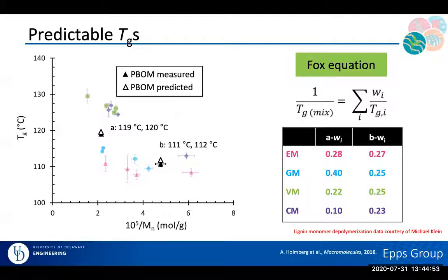So one in particular was this, where we were able to take kraft pine lignin, and we were able to think about it in the following way. In collaboration with Mike Klein, formerly University of Delaware in chemical engineering, he actually did some computational catalysis studies on the depolymerization of kraft pine lignin. When he did those studies, what he was able to come up with is, under two different depolymerization conditions, these are the compositions of feedstocks that we could expect to come out of that process.